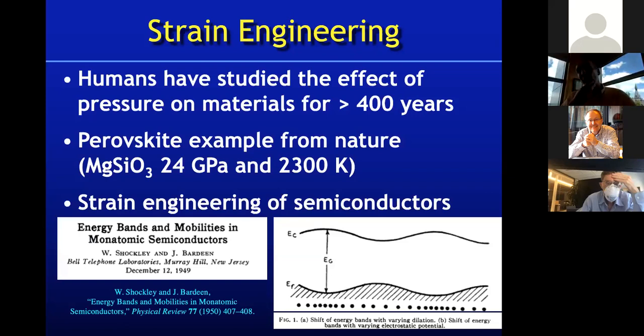Now, an important difference between using strain to benefit semiconductors and what I'll be talking about in this lecture is that it's one thing to take the existing ground state and improve its properties. That's what's done in silicon transistors. It's still in the diamond cubic structure, but by applying the right kind of strain, depending on the doping and the orientation, one can boost the mobility.